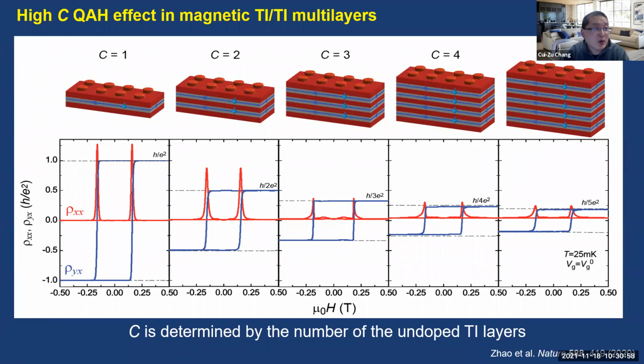This is a growth question, actually a very good question. We know that there is a very famous theoretical prediction. If we further increase the periods of the magnetic TI and TI bilayer structure, when the Chern number is above some critical value, for example, we call it C0, according to the theoretical prediction you should realize the Weyl semimetal phase. This is a very unique Weyl semimetal phase.